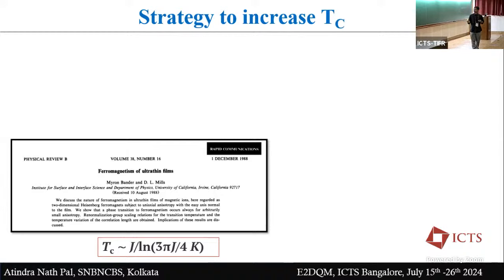You can get an analytical expression of the TC, which is J divided by the log of 3πJ by 4K. K is the measure of anisotropy, and J is the exchange interaction coefficient. In the 3D case, this TC is solely determined by J, so you have around 1000 Kelvin for iron, for example. But if you go to the 2D limit, this K comes into the picture and your TC decreases.